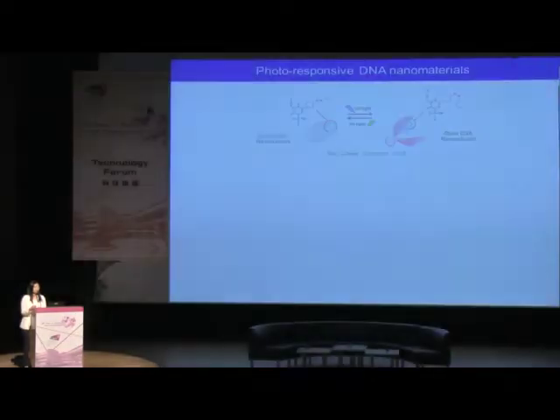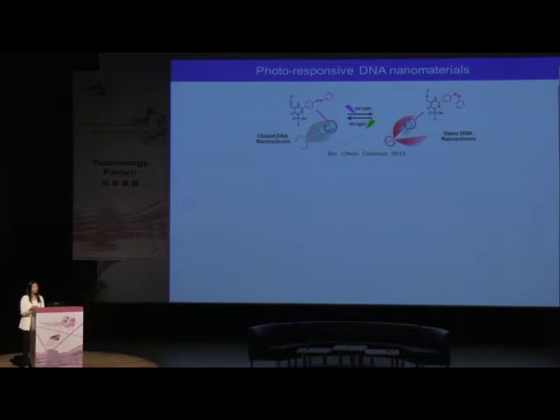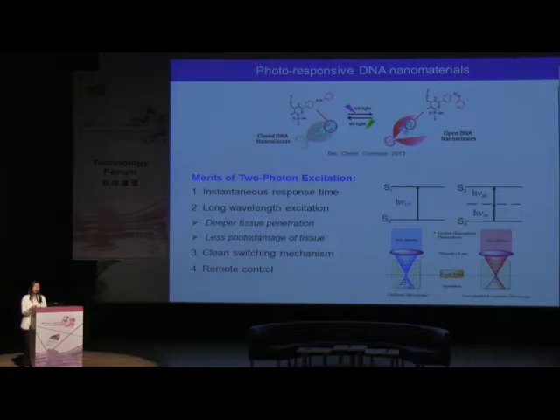So recently, Tang group also tried another approach, using light, to induce the molecular change inside this DNA nanocage. But we know that using UV light basically can cause serious damage to the cell and also has less tissue penetration. So our idea here for biological applications is to use a two-photon excitation as a nice source to eliminate the stimulus, because this kind of approach can give an instant response time, and also this is a long wavelength excitation which will allow for deep tissue penetration and less photo damage of tissue. And again, since no waste is accumulating in this approach, it is a clean switching mechanism. And more importantly, we can remotely control and optimize the entire process.